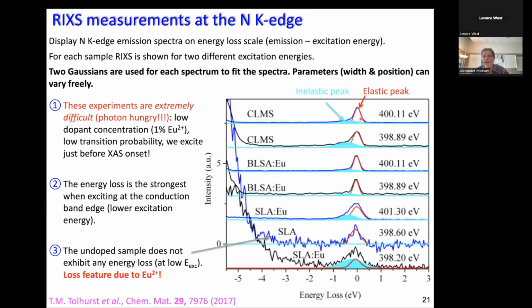So that is why we have now taken fits, and we have always fit. The elastic peak is in red, the blue is the spectrum, and then we have now what's called an energy loss feature, which are these broad sign features. Okay, it shouldn't bother us for the moment that we have 2 different excitation energies. This is a little bit too detailed, but I can explain it if you want to know. So the first thing I would like to note is we have here in the bottom, the SLA without doping, and the SLA, this spectrum here with europium, is the doped sample.